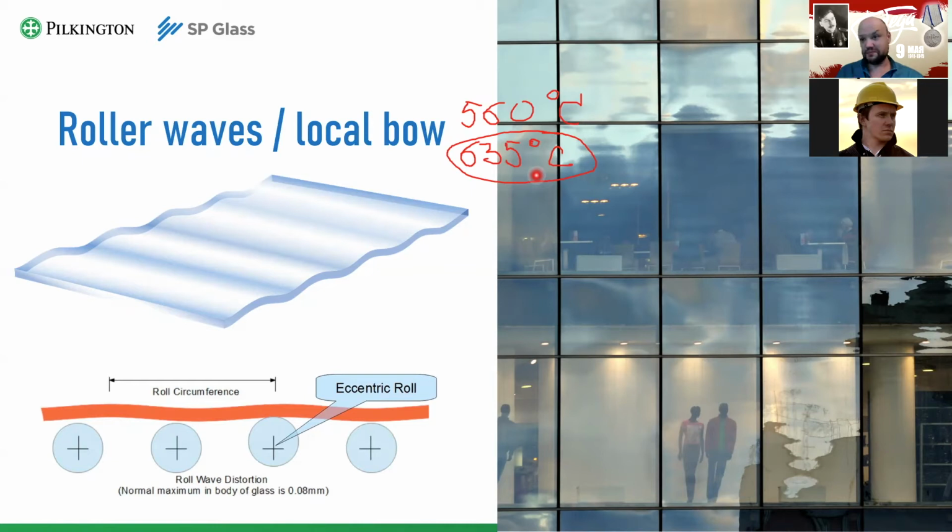For 10mm glass, overheating the glass by 10 seconds is no problem. The thing is, if you overheat the glass, you get the roller wave. If you underheat, if you do not heat your glass enough, it will break in the cooling chamber. So if you're tempering glass, you're always in this dilemma. If you overheat it too much, the customer will be unhappy. If you underheat it, you will break the whole table of glass, and then the boss comes and gives it to you for that.